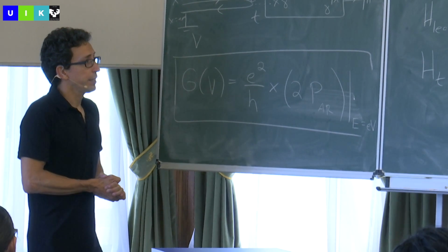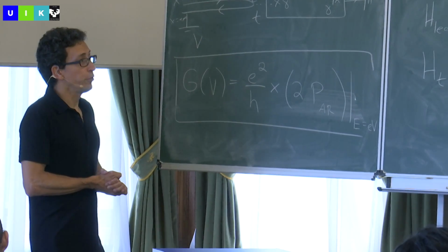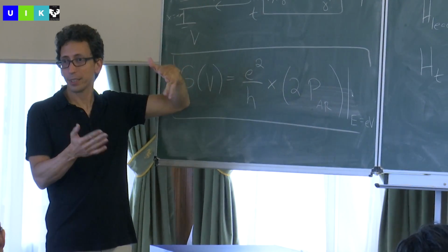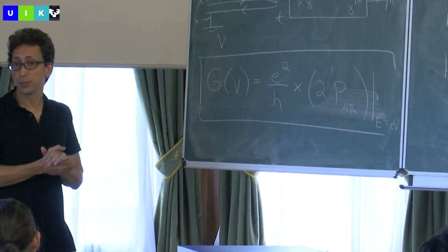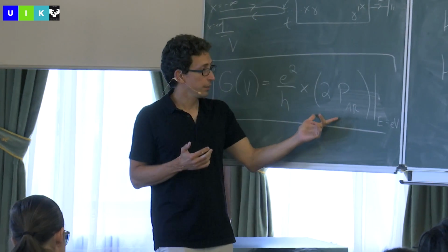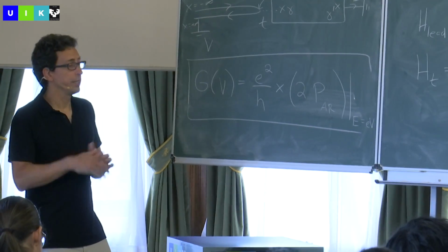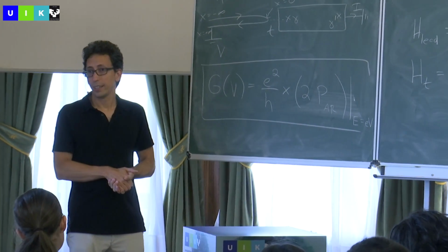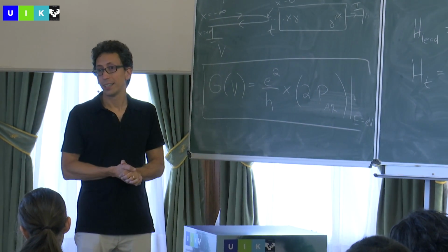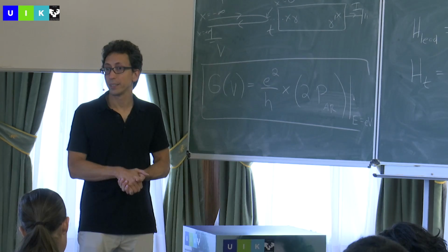Now, if you, let's say, had a non-topological superconductor, suppose I add spin, because that is actually important for getting Andreev processes at low energies in non-topological superconductors. With a spinful lead, the zero bias conductance is actually non-universal, at least within some treatment of this type. And you can get anything from 0 to 4 e squared over h. And it could be that maybe the system happens to have a conductance which is close to 2 e squared over h. It could be accidental, the result of fine-tuning, maybe the result of hunting around in parameter space.